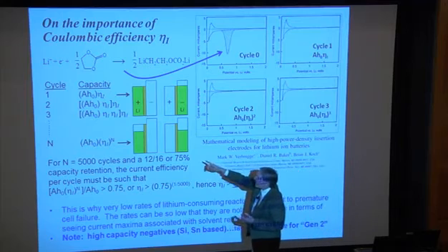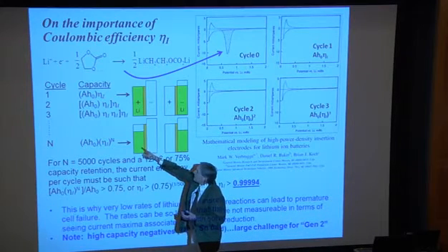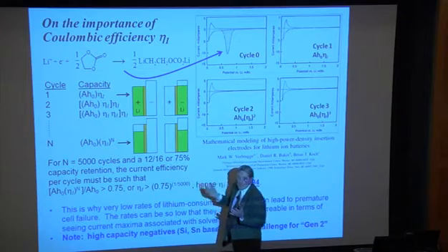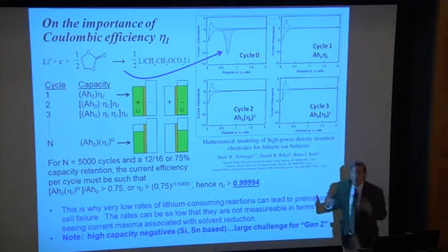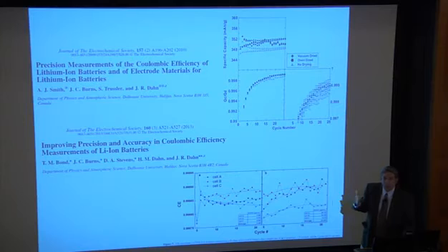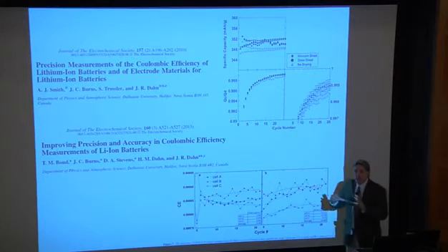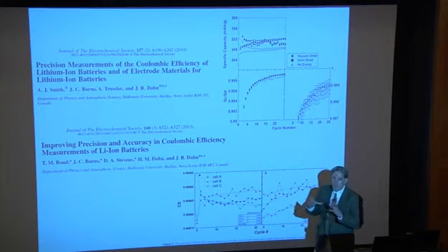And so just as I drew in that little schematic before, you're consuming lithium, you lose it. Your host materials are still active. They still have sites available for lithium. You just don't have lithium to go in them because you've consumed it by this SEI reaction. It's ending up on the negative electrode surface as inert solid electrolyte interphase and other junk that forms at the surface.